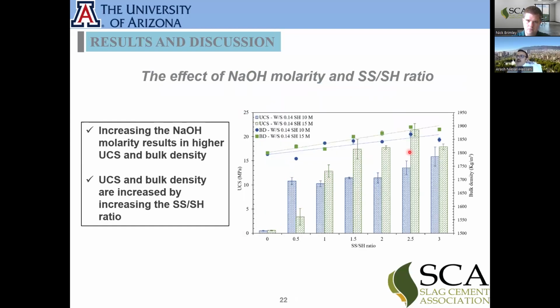So with this graph, now we are going to discuss some of the results. This graph shows the sodium hydroxide alkalinity. So if we use 10 mole or 15 mole, and then we use the SS over SH ratio. The blue bars show the 10 mole sodium hydroxide, and the green one shows 15, so it's higher alkalinity. And you see, by increasing the alkalinity of the alkaline activator solution, we are having a better and stronger geopolymer.